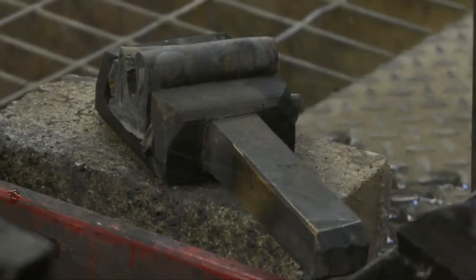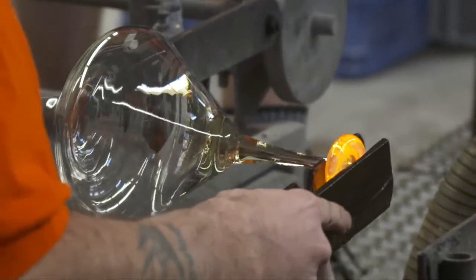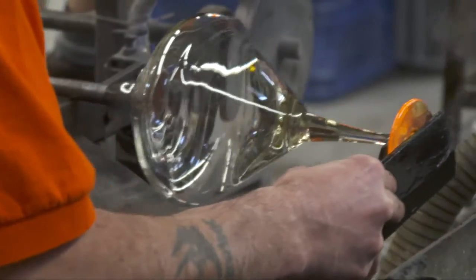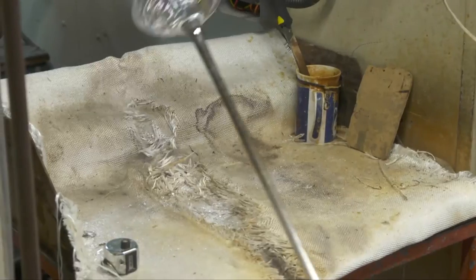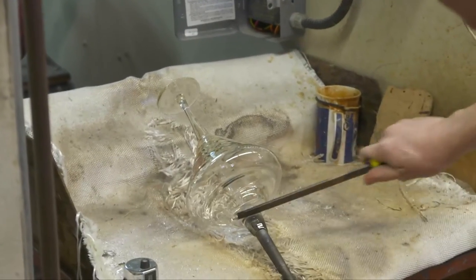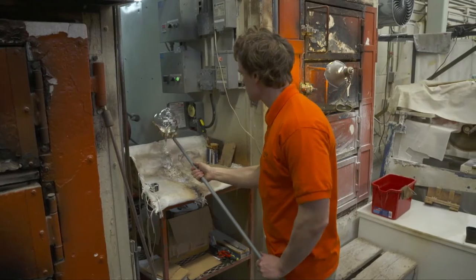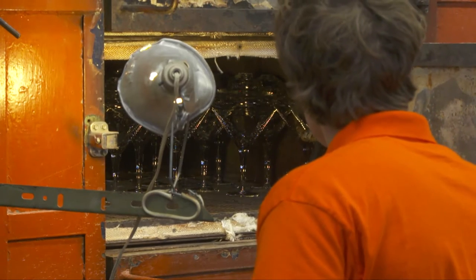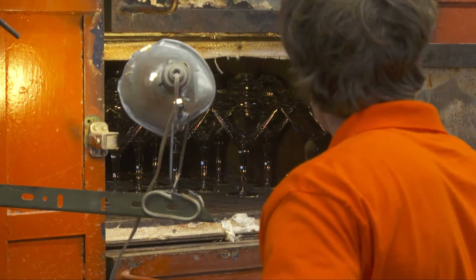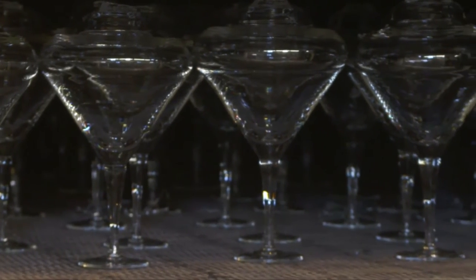The wooden tools are made in Nova Scotia out of cherry or pear wood. This flame on the turning aid keeps the next piece warm while keeping it moving. The molten crystal is cooling as the craftsmen work — the color changes as it changes temperature. The piece is now ready to be removed from the iron. The piece is knocked off the iron, then placed into a kiln to remain at a consistent temperature of 400 degrees Celsius for the rest of the workday.